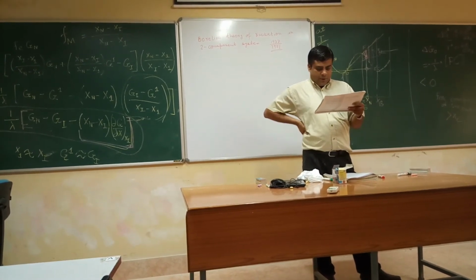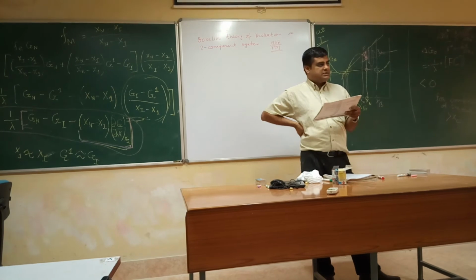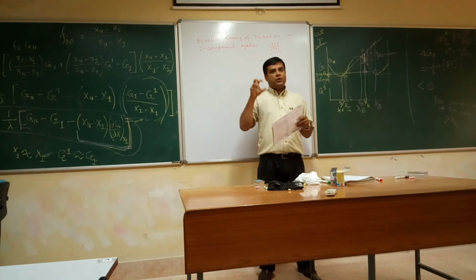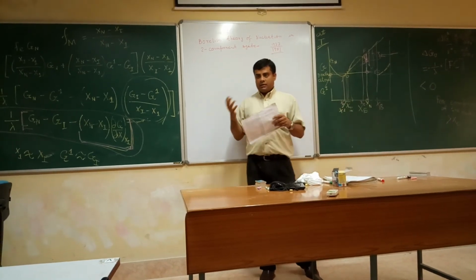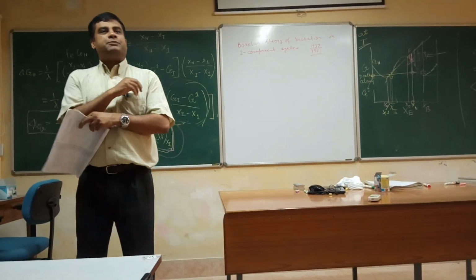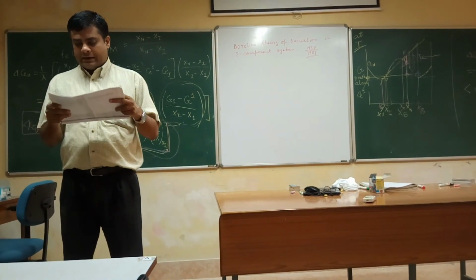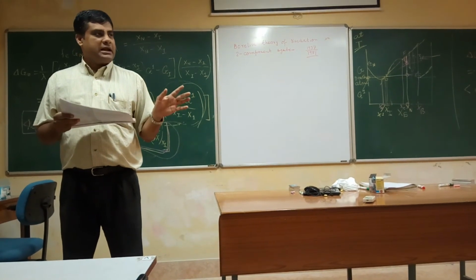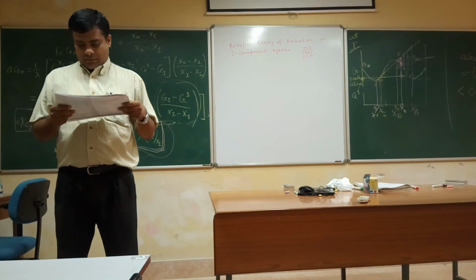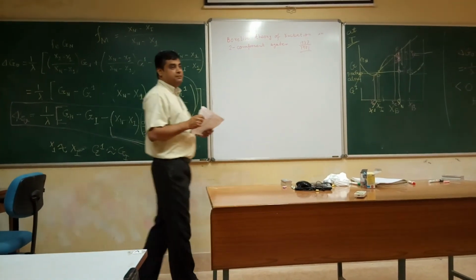The type of system assumed is similar to that in the Becker treatment, in that strain energies were neglected. When can you neglect the strain energy? When your product volume will be the same as the matrix volume, that is, the molar volume will be the same, or if the product is forming in liquid. So in those cases, strain energy can be neglected. In classical nucleation theory, strain energy has been neglected. In addition, interfacial energy was also neglected for Borelius theory.